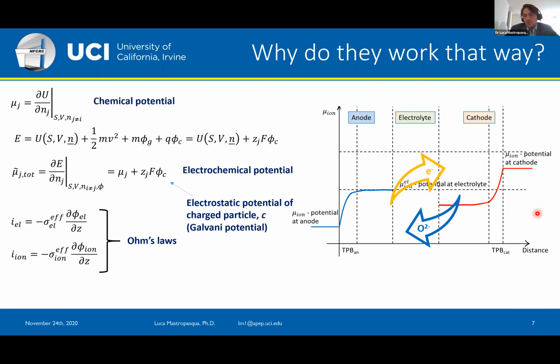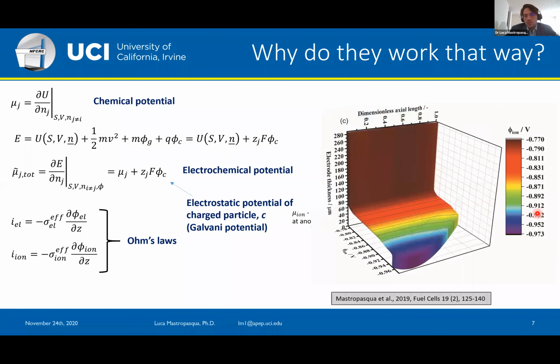And we've done this exercise to plot quantitatively this electrochemical potential gradient in a solid oxide fuel cell fed with natural gas in a planar geometry. And so you see a 3D chart for the ionic potential reported on this axis for the electrolyte thickness and across a channel for a planar fuel cell.